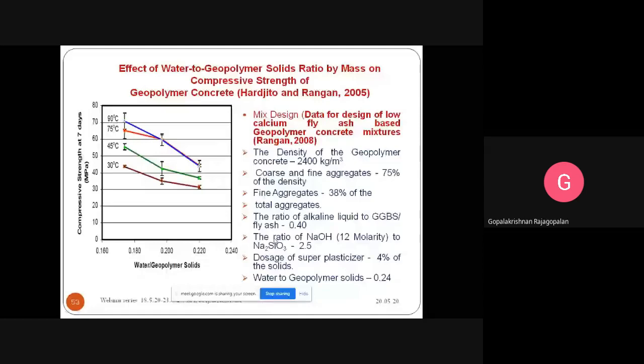Similarly, the ratio of alkaline liquid to GGBS or fly ash. We can use GGBS or fly ash. The ratio of alkaline liquid, that is sodium hydroxide plus sodium silicate, to GGBS is equal to 0.4, which I have taken. Other things are similar: coarse and fine aggregate, and then the density we are assuming. So this graph will be very useful to determine the mix design for the geopolymer concrete. Once the mix design has been identified, that's all.